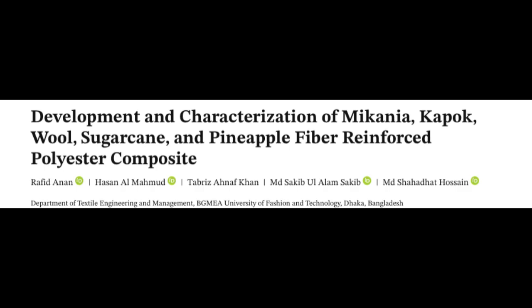And what did that super-powered microscope, the SEM, tell them about how well these fibers mixed with the polyester? Was it all smooth sailing? Not entirely. The SEM images revealed that the different fibers had varying levels of dispersion within the polyester. Meaning how evenly spread out they were. Exactly. And the quality of the bond between the fiber and the resin also differed. For some, like Mikania and pineapple, actually. Even pineapple? Yeah, they saw areas where the fibers weren't spread out as evenly as they could be, and there were even some small air pockets or voids. And voids are bad, right? Weak points. Definitely weaken the composite. This suggests that there's room for improvement in how these materials are processed to get a better, more uniform blend,